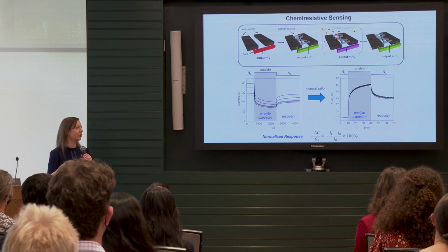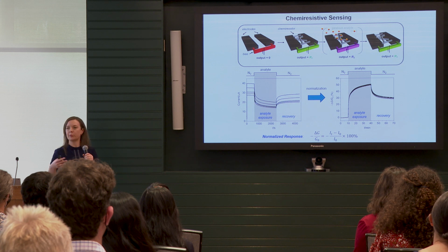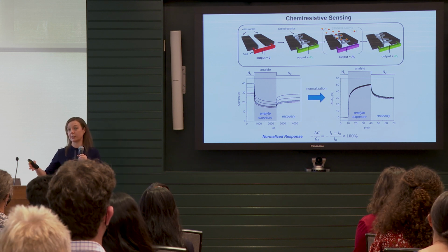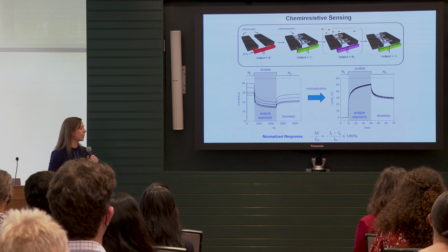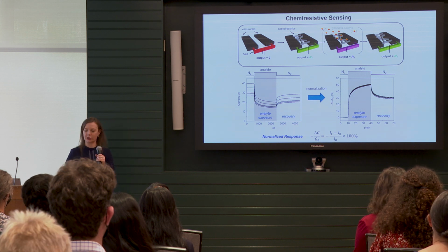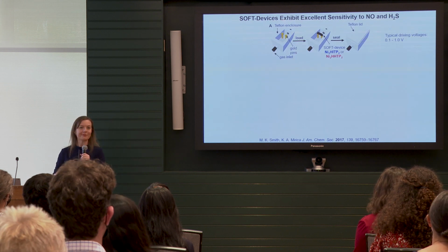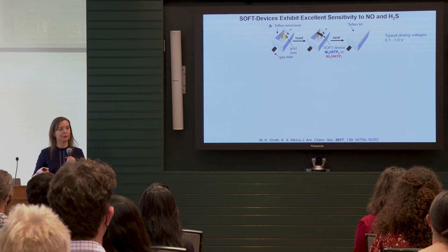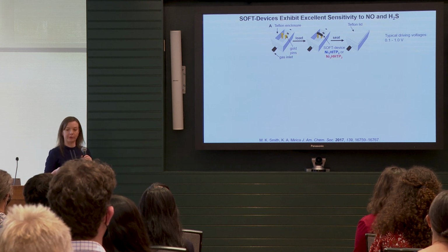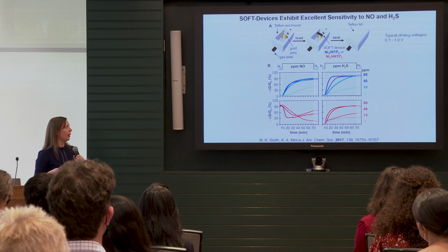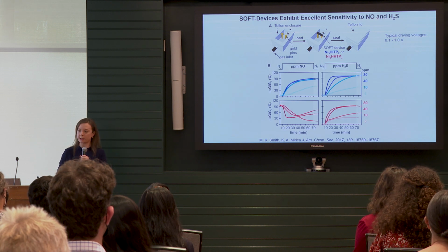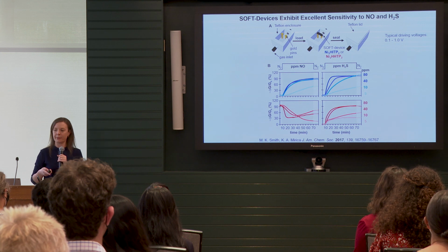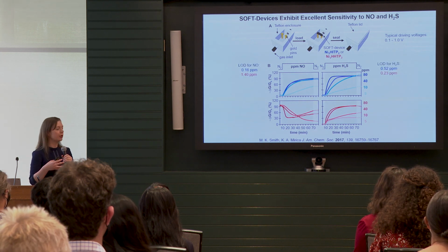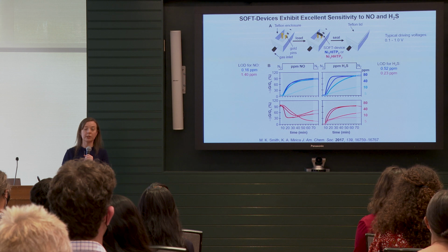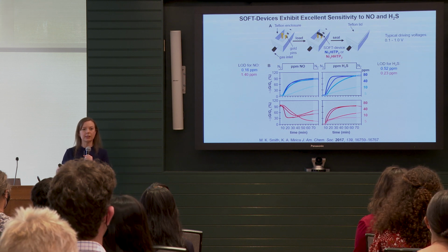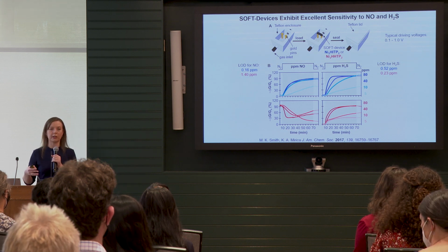And the sensing response in the traces that I will show is basically proportional to the electronic resistance within the device. So when you're looking at these plots of negative delta G over G0, just think of it as resistance. Taking our electronic textile swatch and applying constant voltage and measuring current gives us the following responses to nitric oxide and hydrogen sulfide. I want to point out that from the concentration-dependent response, we can derive limits of detection, so we're able to detect these analytes at sub-part per million concentrations.